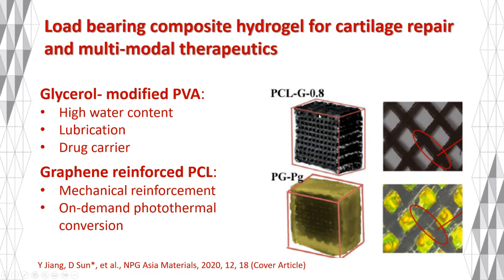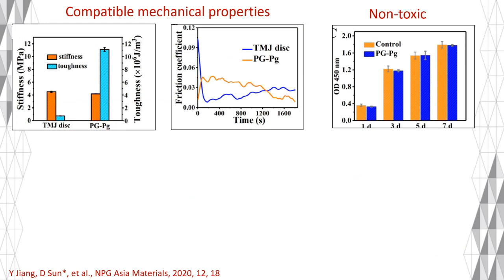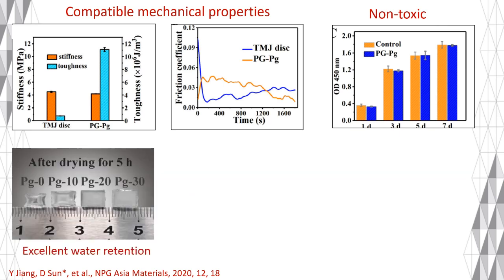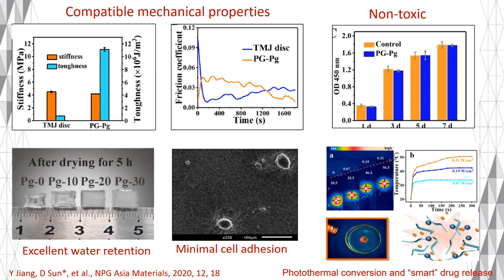Additionally, we reinforced the hydrogel by incorporating a 3D printed PCL graphene nanoplatelet composite scaffold to enhance the overall mechanical properties of the scaffold system. The implant we developed successfully achieved mechanical and lubrication properties comparable to natural cartilage, and it also offers excellent biocompatibility. Additionally, it exhibits high water retention and low cell adhesion, which are highly desirable for cartilage applications. Furthermore, the incorporation of graphene again enabled stimuli-responsive drug release properties, which can be controlled by laser irradiation.